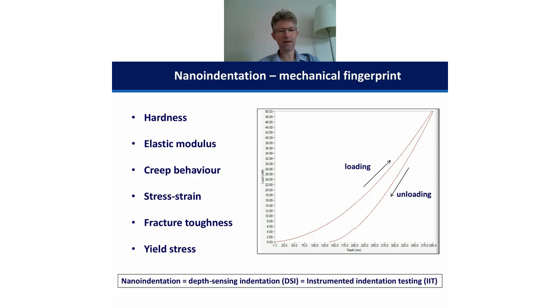We can design different tests, as Andy described, to look at time-dependent deformation. We can move to spherical indenters to look at stress-strain behavior. We can also look at yield stress, as one of the questions just now. To get yield stress out of an indentation test, you have a couple of different approaches. You can measure hardness, and then use the constraint factor to relate hardness to yield stress. The constraint factor is about 3 for metallic materials, but a lot less for ceramic materials, so that gives you a reasonable estimate of yield stress.